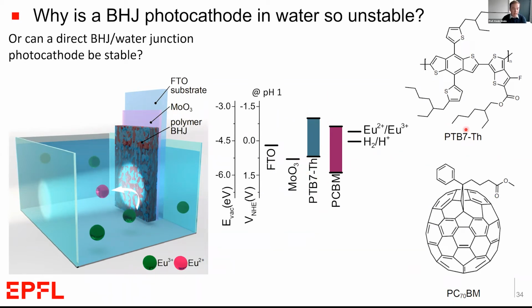We used PTB7-Th and this PCBM, C70, which should be able to reduce europium. And we note that the energy level of the europium is higher than that of the hydrogen reduction, so that if we can reduce europium thermodynamically, we should be able to reduce hydrogen as well. But this reaction should be a lot easier, just a simple 1 electron outer sphere reaction.